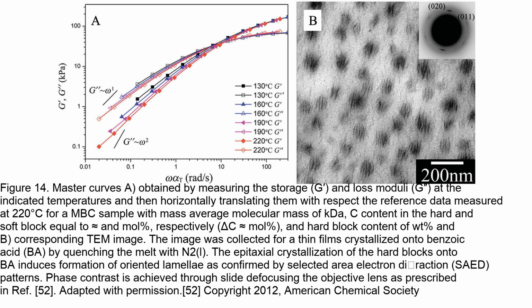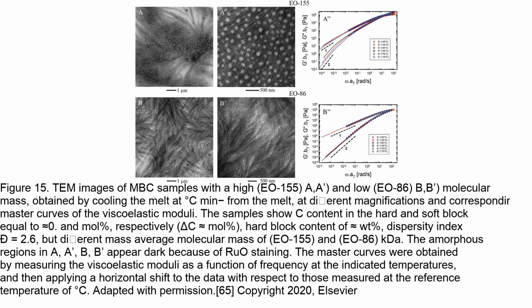morphology upon quenching. The paper shows TEM images and viscoelastic moduli master curves of two MBC samples with similar chain microstructure but different mass average molecular mass of approximately 155 kDa, EO155, and 86 kDa, EO86. The samples have a C8 content of approximately 0 and 20 mol% in the hard and soft blocks, respectively, and a hard block content of approximately 27 wt%.